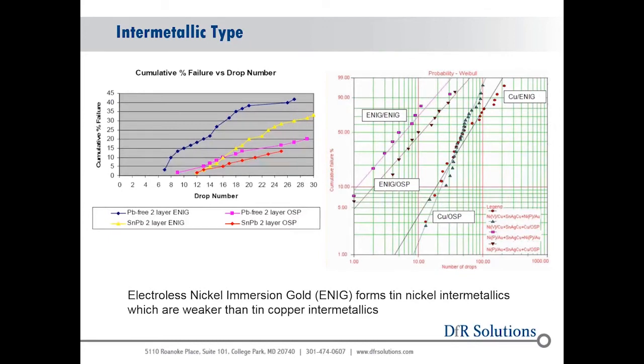As I was saying earlier, there's tin copper intermetallics, there's tin nickel intermetallics. Electroless nickel immersion gold, ENIG, is the gold finish on your boards. It's just a very thin layer of gold over top of nickel. The standard intermetallic form would be tin nickel. For any of the other board finishes, such as OSP, immersion tin, immersion silver, HASL, you're going to be forming copper tin intermetallics.